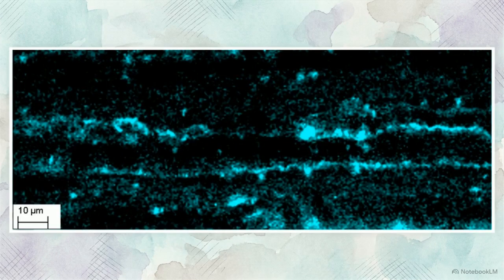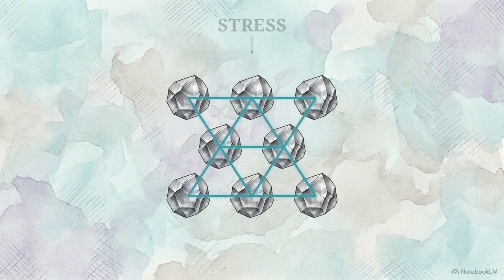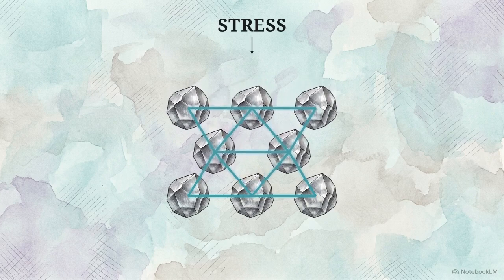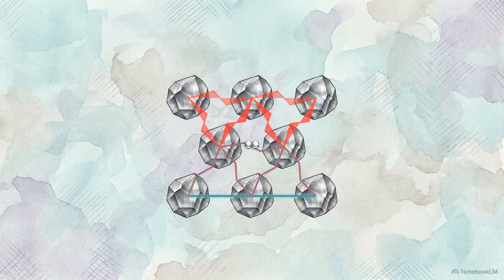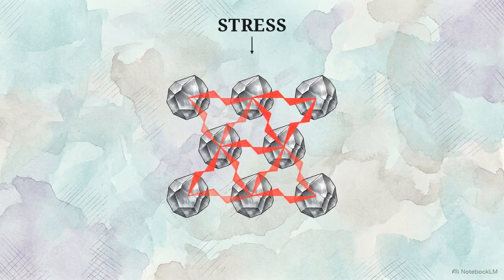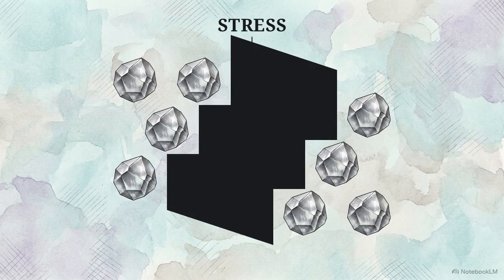This spectral scan provides the evidence. Bright teal horizontal traces are gallium, showing where the liquid metal settled inside the aluminum. It doesn't attack randomly. It precisely targets and saturates the pathways between grains, exploiting the boundaries that hold the aluminum together. At the atomic level, gallium wedges into these boundaries, replacing strong aluminum bonds with weaker aluminum-gallium bonds. Normally, grains slide past each other, allowing the metal to bend. Now that ability is lost. Instead of flexing, the grains separate and the material shatters.